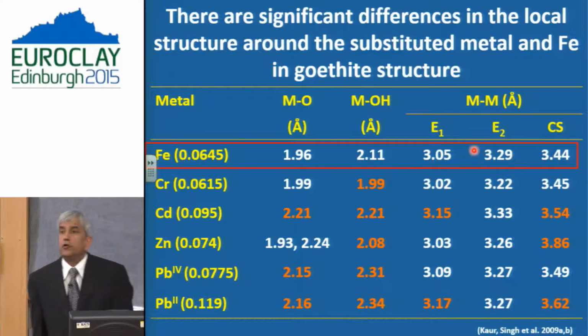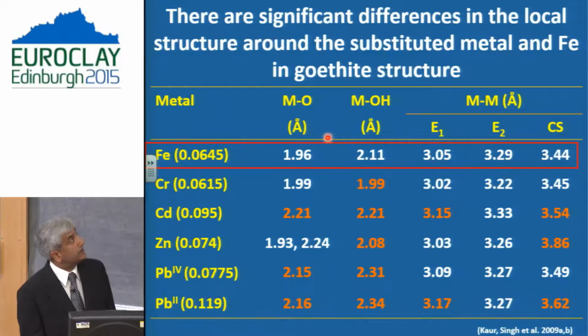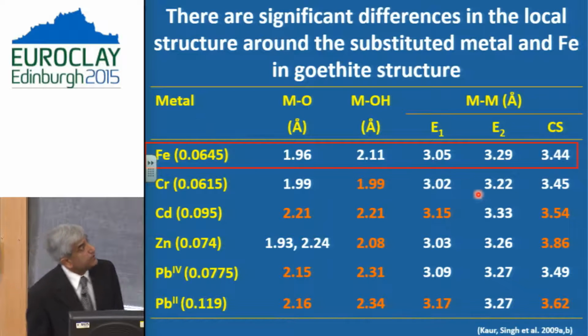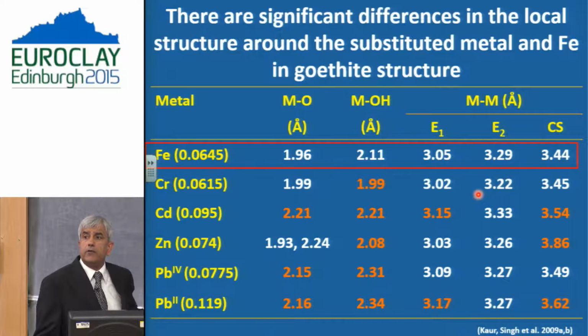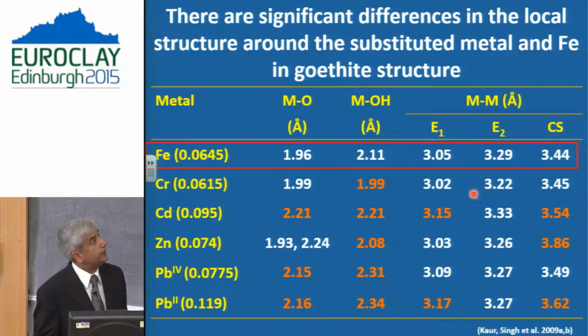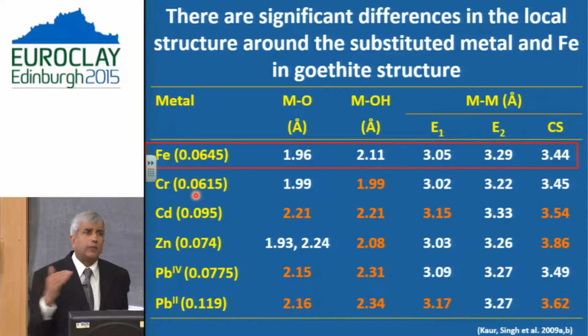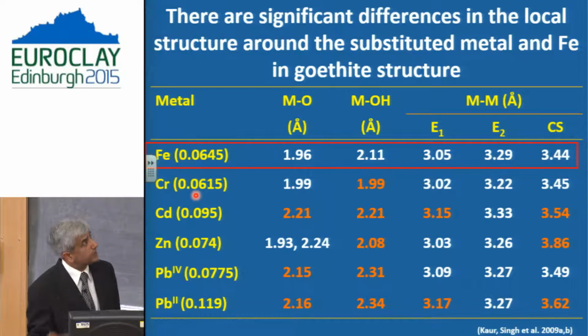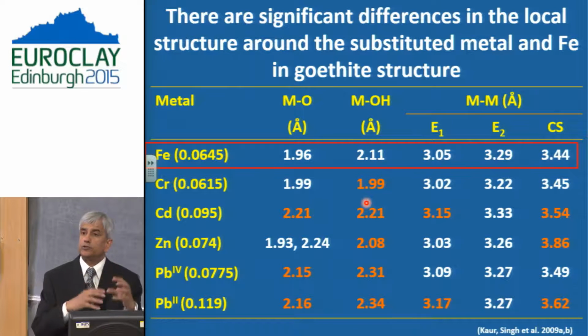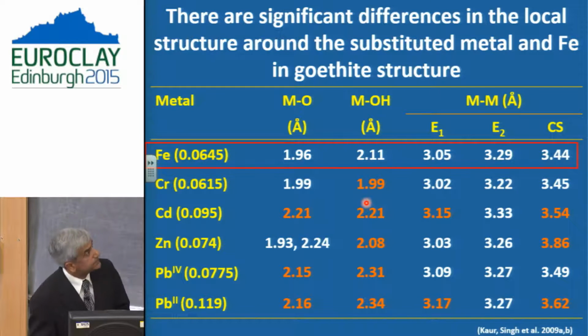When you look at the local structure for the metal substituted systems, you see that there is clear evidence of distortion of the octahedra or of the local structure. In case of chromium, where we are about to fit about 10 mole% of chromium in the structure, you can see that the metal oxygen distances were similar. You were not able to separate the oxygen and hydroxyl distances.